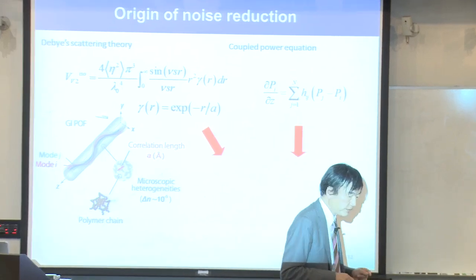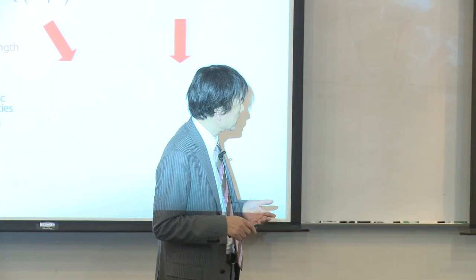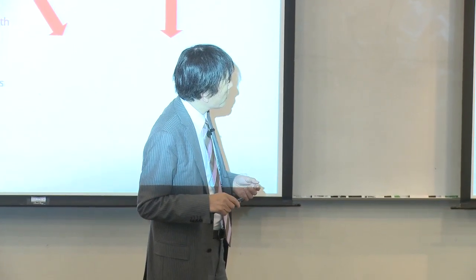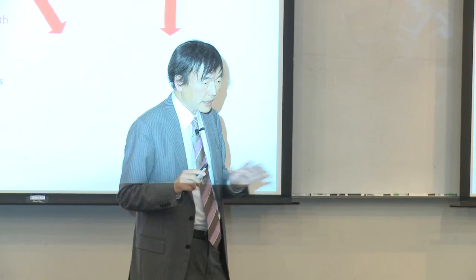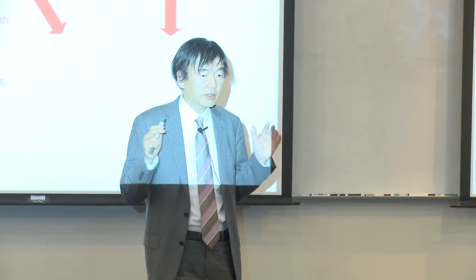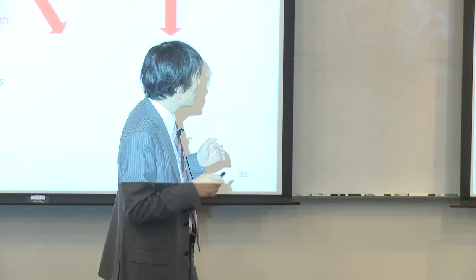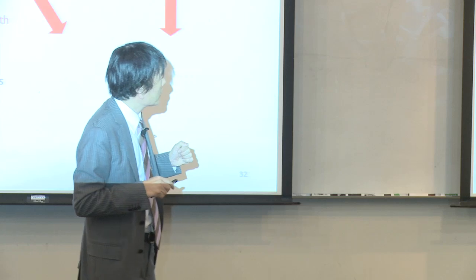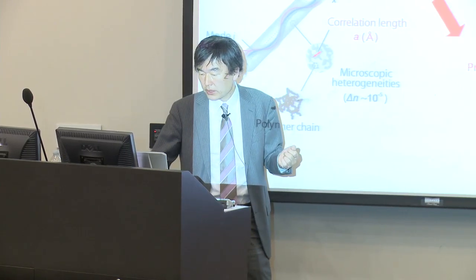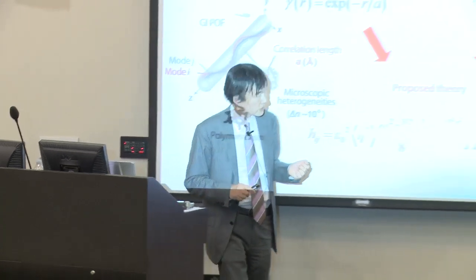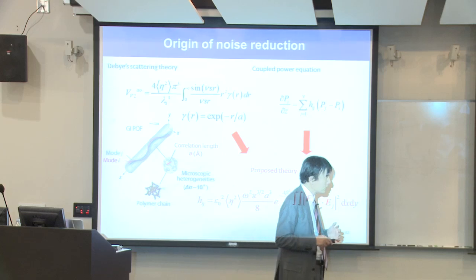It's not perfectly analyzed, but so far, especially at Bell Labs, leading the study on optical fiber communications, they developed a coupled power equation that is a very famous one. But they neglect the tiny fluctuation in the glass material. But in plastic fiber, certainly there is some heterogeneous structure, as I explained. So this is a tiny one and has been overlooked. But utilizing the Debye equation, we know the correlation between the scattering and the microstructures. So joining the two different equations should give this. This is the one we would like to propose.